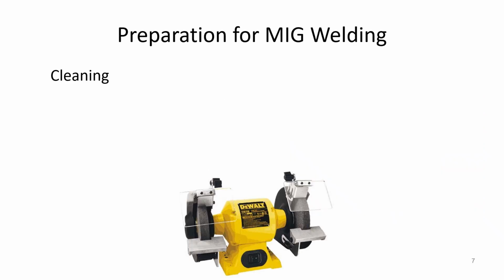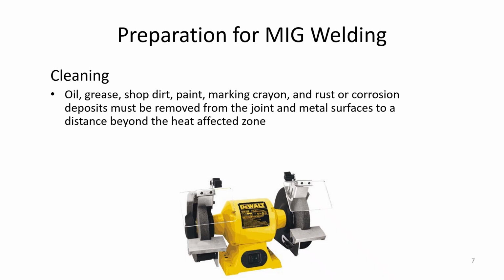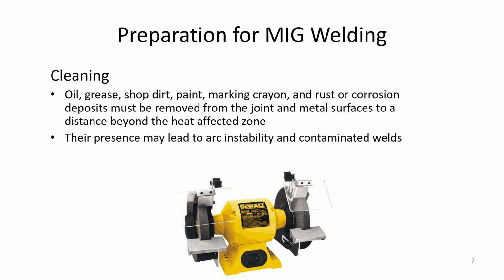it's possible. So when we're cleaning for MIG welding, gas metal arc welding, any kind of oil, grease, shop paint, any of that, it's got to be removed from the metal surfaces, and it's got to be removed probably 2-3 inches back, far enough out so that it isn't in the heat affected zone. Any kind of presence of this stuff, we can get arc instability and contaminated welds. So you've got to have it clean before you weld with the GMAW or the MIG welding process.